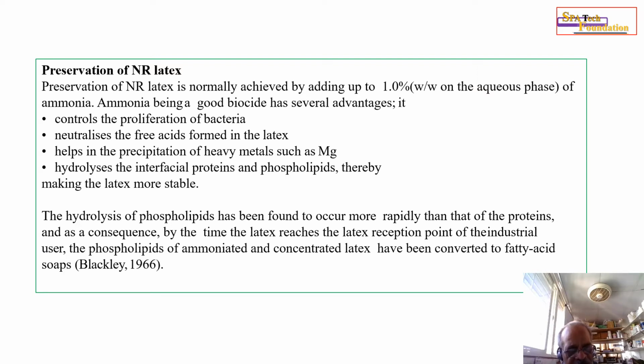Preservation of natural rubber latex. Preservation of natural rubber latex is normally achieved by adding up to 1% by weight of ammonia. Ammonia, being a good biocide, has several advantages. It controls the proliferation of bacteria, neutralizes the free acids formed in the latex, helps in the precipitation of heavy metals such as magnesium, and hydrolyses the interfacial proteins and phospholipids, thereby making the latex more stable.